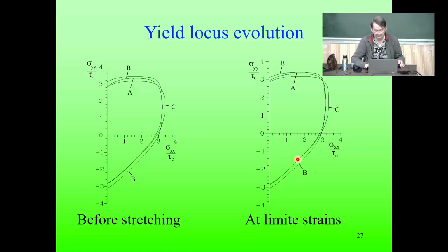We can look at the evolution of the yield locus, the yield surface, also during deformation. So here we see A, B, and C, the three materials. The yield surfaces, yield functions are plotted here. And there are changes, but not very dramatic changes in the shapes of the yield surfaces, because basically the strains are not that much. So in the shape, not really much is expected to change.